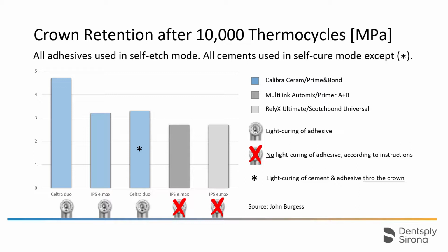After 10,000 cycles of so-called thermal shock stress, in which crowns cemented to tooth structure are stressed by temperature fluctuations between 5 and 55 degrees Celsius, the crowns were removed from their dies and the force required to remove them measured. The cemented crowns were fabricated using the silicate, respectively, glass ceramic Celtra Duo from Dentsply Sirona and IPS Emax from Ivoclar Vivadent. Calibra Ceram and competitors' products Multilink Automix and RelyX Ultimate were used for cementation according to the instructions for use. Calibra Ceram showed superior results in combination with IPS Emax, but with Celtra Duo in particular.